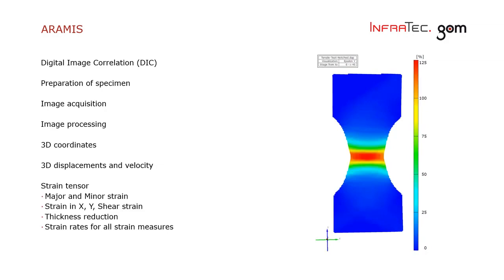A strain tensor is further on calculated through the 3D coordinates, so the displacements between the 3D measurement points is analyzed for major minor strain evaluations as well as strains in X and Y direction. Shear strain can be calculated based on the volume constancy of materials, so usually talking about sheet metal parts. The thickness reduction is a calculated result value as well as strain rates for all of these measures due to the time-based image acquisition.